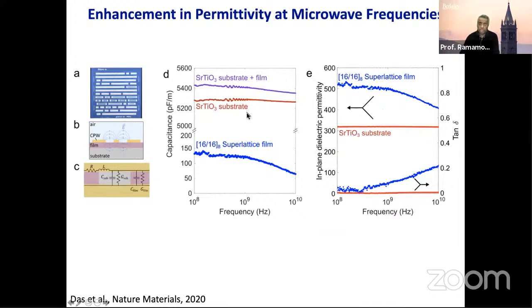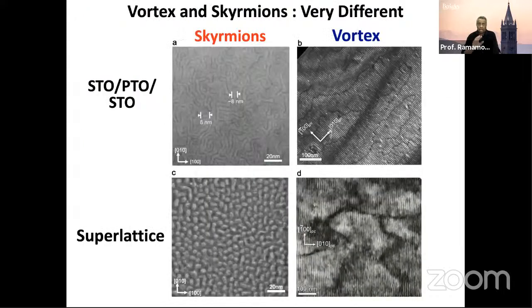All right, and it turns out that because of this negative permittivity, you can have very large enhancements in the dielectric permittivity all the way up to, this shows 10 gigahertz. We now have data all the way up to 100 gigahertz that it has very large dielectric permittivity. And clearly these are of interest for microwave circuits and stuff like that. The fact that you can tune the dielectric permittivity with an electric field is very valuable. And it's all arising from the negative permittivity at the periphery of the skyrmion. Okay, just to complete the picture, these skyrmions and vortices look very different. They arise for essentially the same kind of reasons.